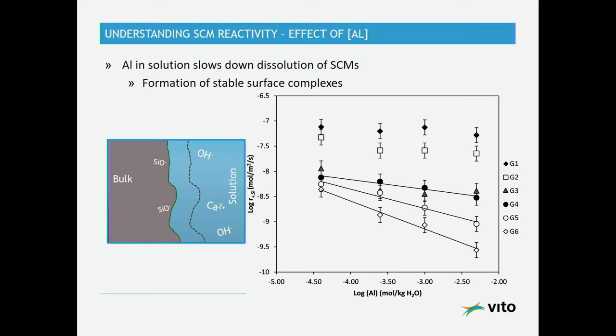And this has been shown before in many other publications as well, that you can actually have aluminum from the solution attaching to the surface of the glass and making passivating or stronger bonds that actually are much more difficult to disintegrate by the hydroxyl solution. So you get really this rate decrease by aluminum. And so now one can think, okay, how can we use these kind of insights in practice? And then maybe one has to think also, okay, what kind of aluminum concentrations do we expect in typical cements?